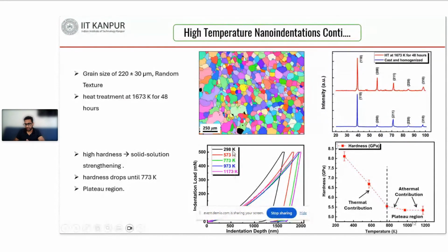So we have done a series of indentation tests at different temperatures, and at a particular temperature we did 5 to 7 tests to get the average value of hardness and indentation. So from this indentation curve we got the hardness and the modulus value.